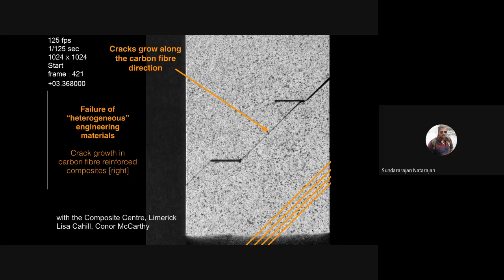along the fiber direction. So now this can help us design structures where we can optimize the layout of the fibers such that if at all there is a crack or a discontinuity, it can delay the fracture process. So you can engineer the fiber orientation such that the crack takes a longer time to grow, which implies that we can increase the life of the component.